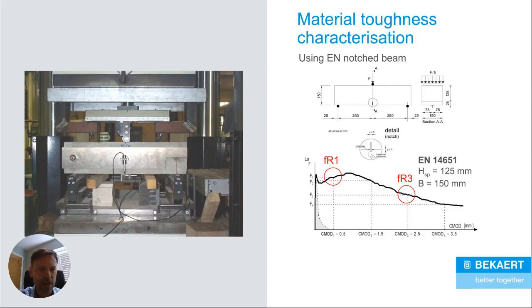This is the setup of the EN test. In the past, steel fibre ductility was measured using a Japanese or American test, but this has been largely superseded in Europe by the European standard, EN 14651. That sample of concrete is 550 millimeters long, with the simple supports spaced at 500 millimeters and a single point load applied to the top.